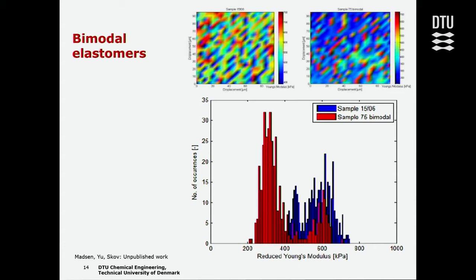So we get a matrix with very low Young's modulus, and then we have the reinforcing red points in our matrix. If we just mix in all our components at once, we see that the picture, of course we have some distribution in the local Young's moduli, but on the other hand, we don't have such a significant difference, because here we simply change from blue to red, and we don't really see these transitions in the traditional way of making elastomers. Again, it's very tedious. We don't get any improvement in the dielectric permittivity, but we can actually decrease the Young's modulus by around a factor of 10 to 20.